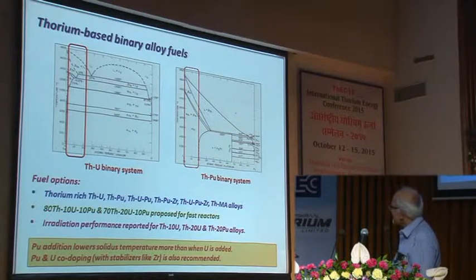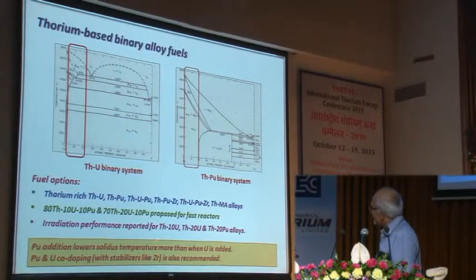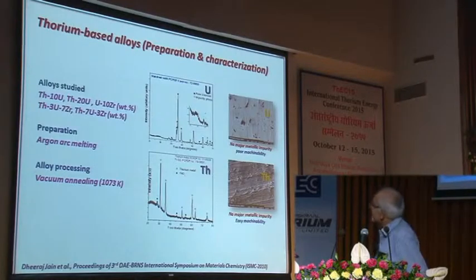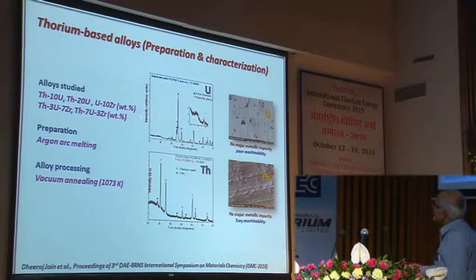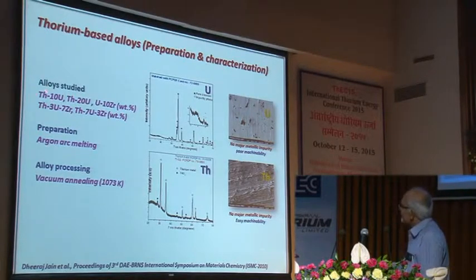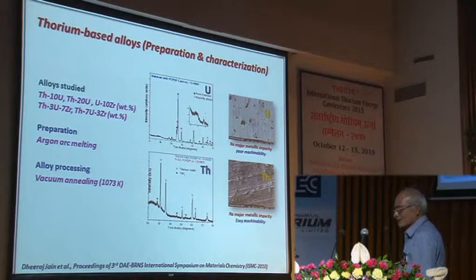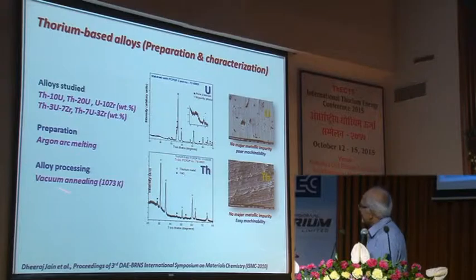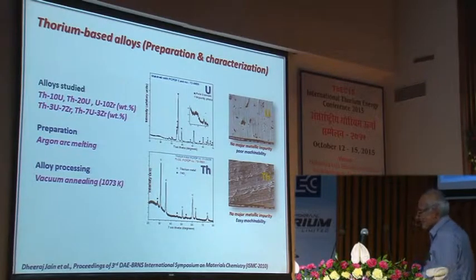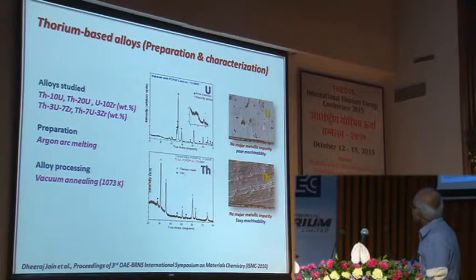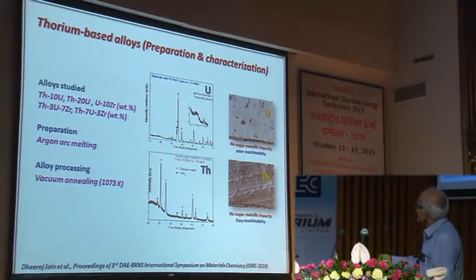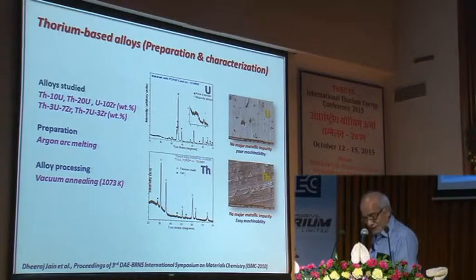And in fact, some of these fuels are proposed for the fast reactors, and some irradiation performances are reported for thorium-10 uranium, thorium-20 uranium, and plutonium alloys. Now, in our laboratories, we have prepared these thorium-based alloys. These are thorium-10 uranium, thorium-20 uranium, uranium-10 zirconium wt%. Also the ternary alloys, thorium-3 uranium-7 zirconium, and so on. The method used here is argon arc melting, and the alloy preparation followed by vacuum annealing at 1073 Kelvin. You can see here this is uranium thorium. Of course, they inherently contain some uranium oxide and thorium oxide.